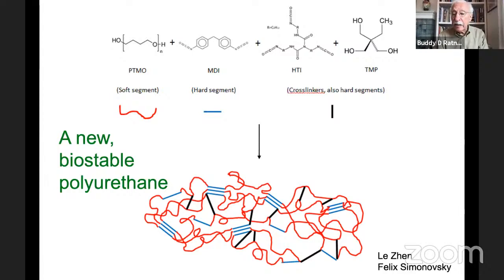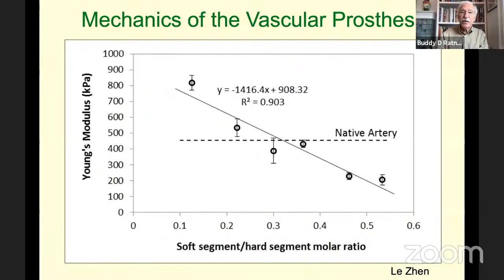PhD student Le Zhen and Dr. Felix Simonovsky, by the way, Le Zhen is now Dr. Le Zhen, got his PhD doing this work, invented a new polyurethane that uses some conventional components, but also uses some very unique cross-linkers that lead to a very biostable polyurethane. And one of the good things about these polyurethanes is we can adjust the components, the ratios of components that go into them to adjust the mechanics of the material. And on the y-axis, we have Young's modulus. And by adjusting the soft segment, hard segment ratios, we can tune the mechanics of these polyurethanes to that of native artery, which is what you see here.